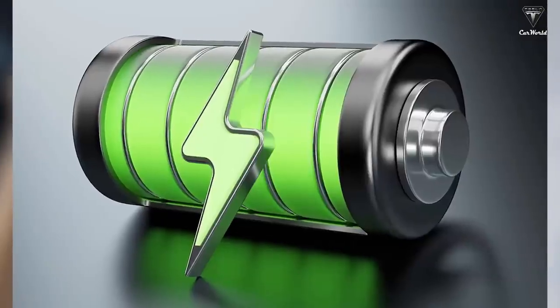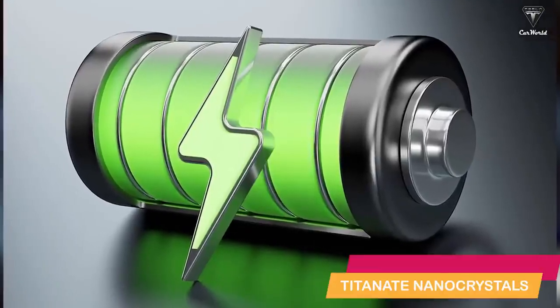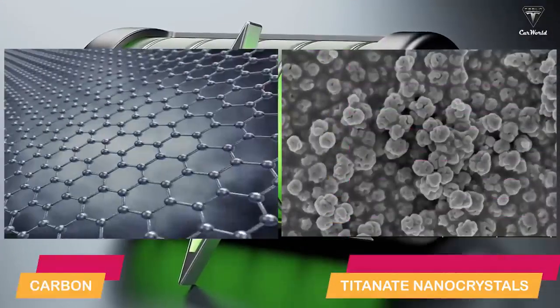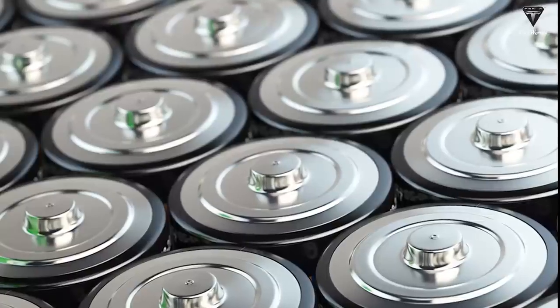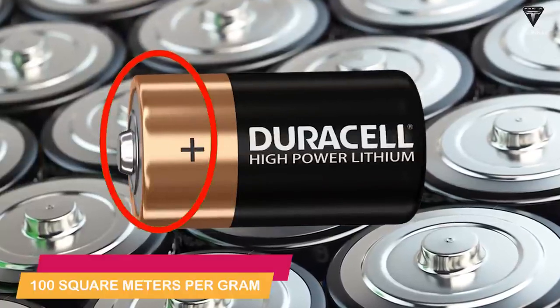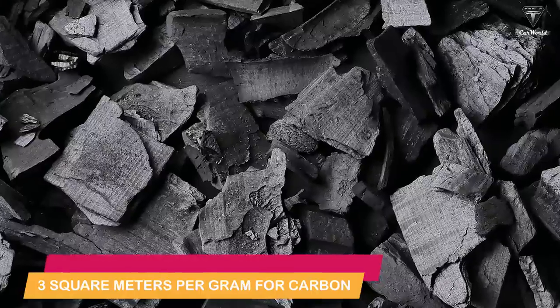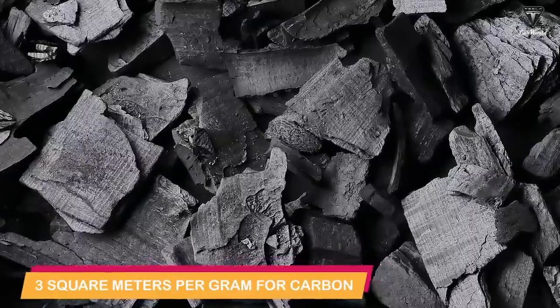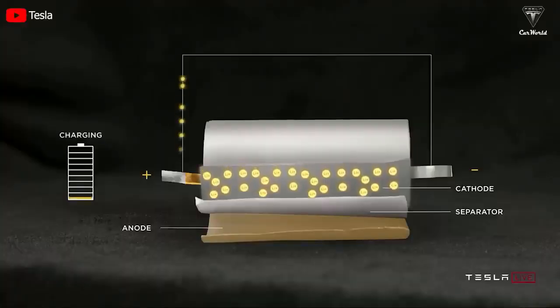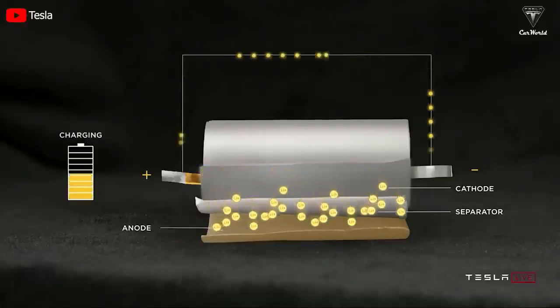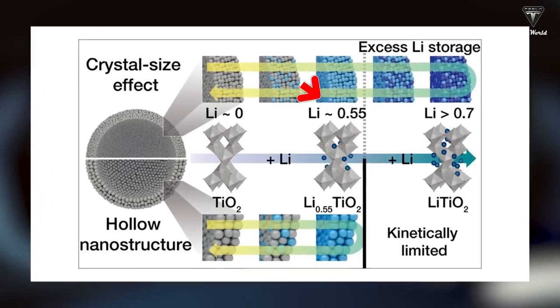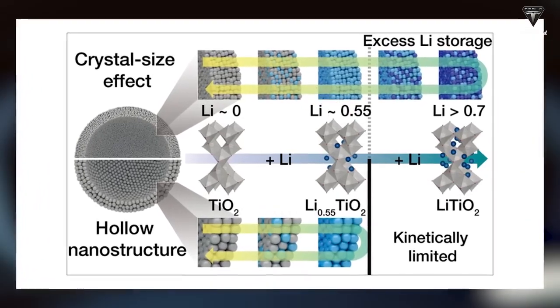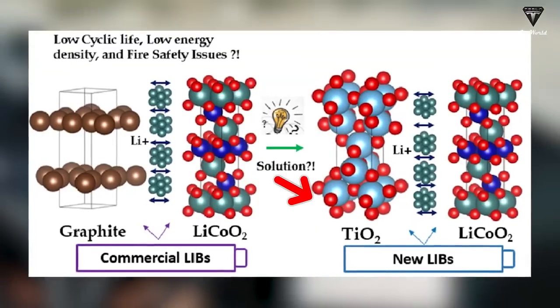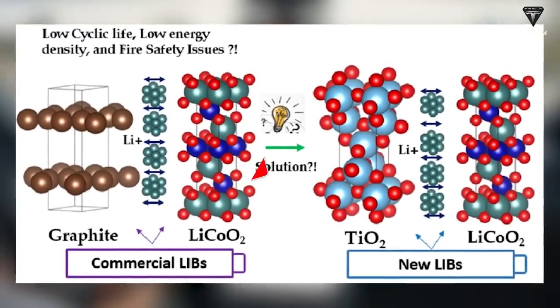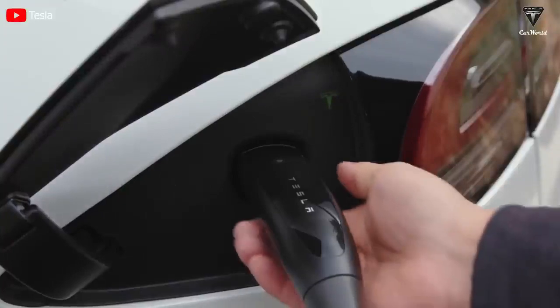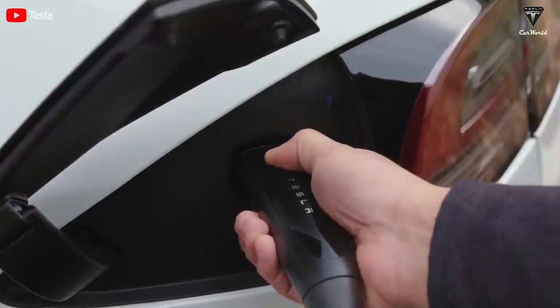On the other hand, the lithium titanate battery utilized titanate nanocrystals instead of carbon on the anode surface. This provides the anode with a surface area of around 100 square meters per gram compared to 3 square meters per gram for carbon. That allows electrons to enter and exit the anode quickly. Furthermore, the redox potential of Li plus intercalation into titanium oxide is higher than that of Li plus intercalation into graphite. Because the charging current is higher, this results in faster charging.